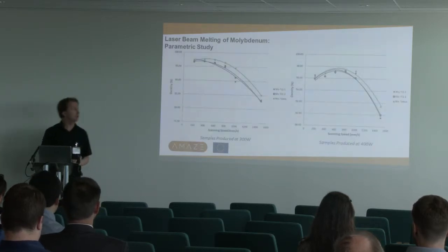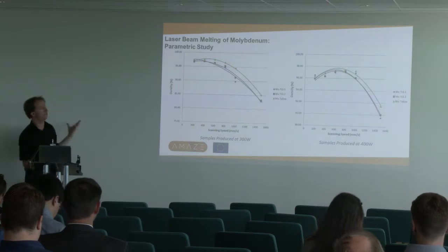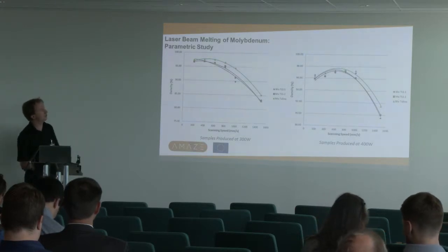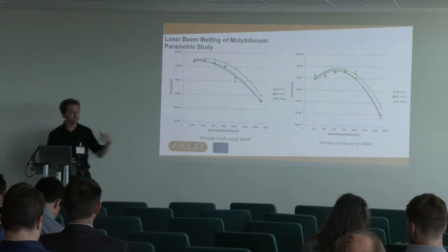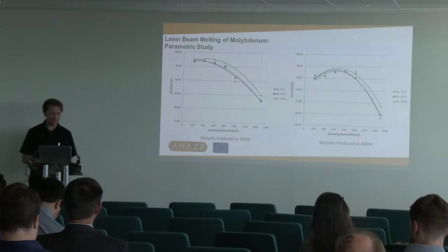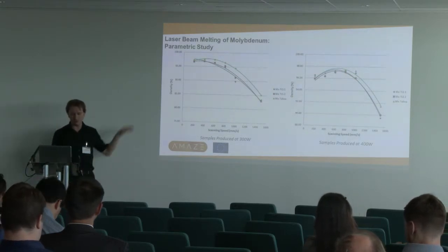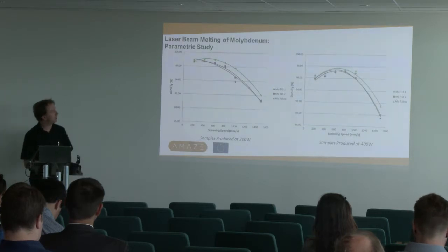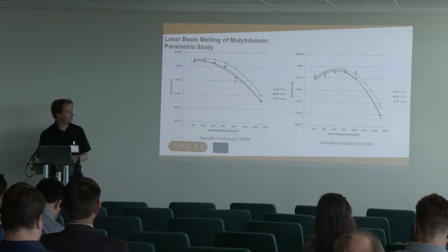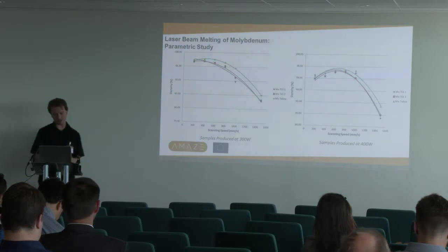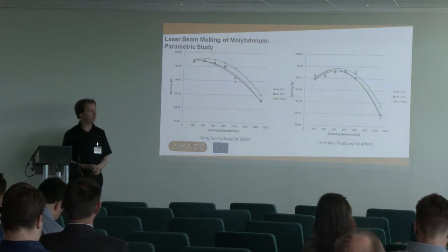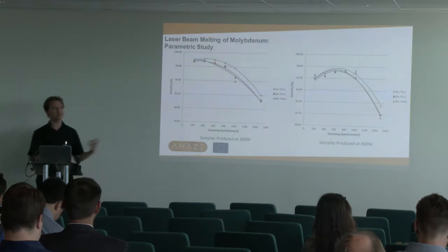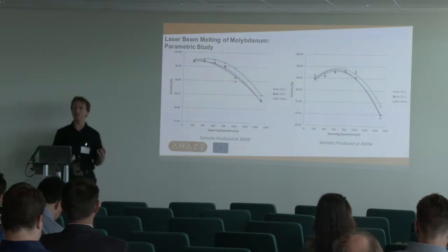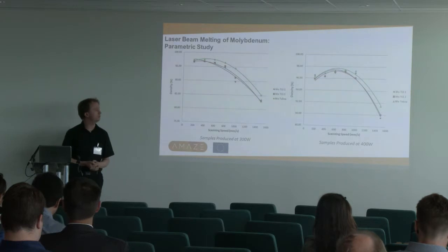It's illustrated a bit better if you look at the individual graphs for the different powers. On the left-hand side, you've got the 300 watts with scan speed across the x-axis, and that Tekna powder is always showing a slightly higher level of consolidation. Likewise, not as clear with the 400, but with the 400 as well, it's still above the other 2 curves, which confirms what you'd imagine, that a nice spherical powder in the size fraction that you want is going to give you a low porosity material.